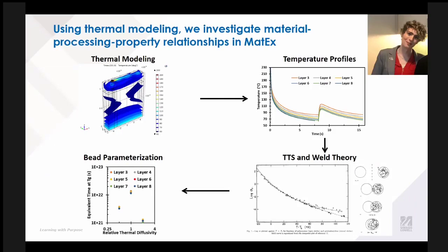So this is work that was primarily performed by a recent graduate from my group, Tone D'Amico, and pretty much everything I'm going to be showing here was led by them. In this work, the approach has been to use finite element based approaches in order to perform thermal modeling. What we're showing here is an example of a geometry, and each of these surfaces shown in color is an isosurface. So all along one of these surfaces would correspond to a temperature. For example, I think that's corresponding to maybe 90 or so. So this top one, then you can see it gets a little bit hotter as we get closer to this heated build plate that would be at the bottom. And then there's an extruder that's being simulated here, where there's the nozzle that's extruding material.